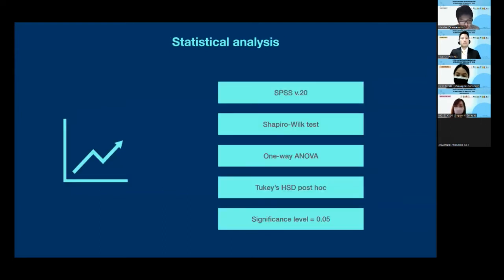Then the data was analyzed using SPSS version 20. The Shapiro-Wilk test was used to test the normal distribution of the data, and we used one-way ANOVA and Tukey post-hoc analysis to compare the mean shear bond strength values. P-value less than 0.05 was considered significant.